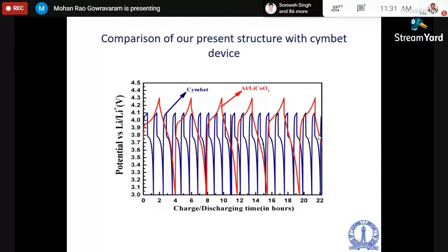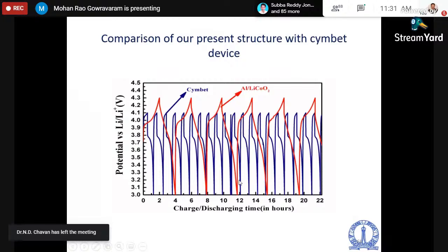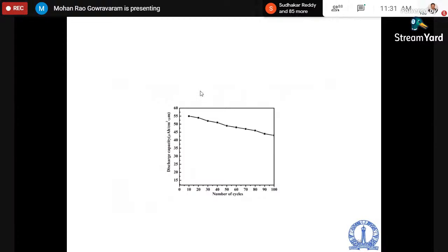So this is the situation. So this battery that we have developed with all these glove box, etc., precautions, looked better than the commercial battery that is made by Cymbet Electronics. So you test its capacity. It gives you 55. Even after 100 cycles, it is still about 45 microampere hours. And then we tested the life further. Life existed in the battery even after about 2000 cycles, though the capacity has come down to about 30 microampere hour per centimeter square. Which means that you know how to make a battery, but you don't know how to package the battery. So if you do an effective packaging, the battery is going to work.